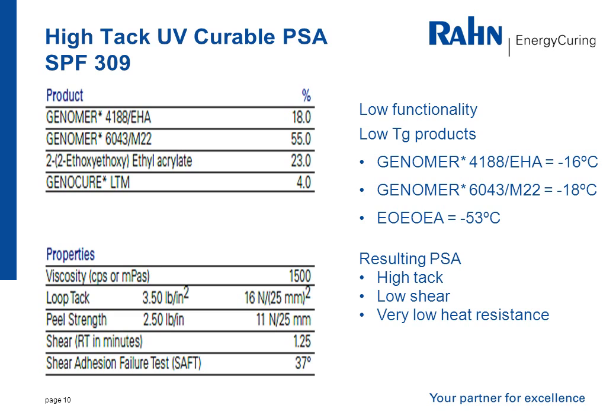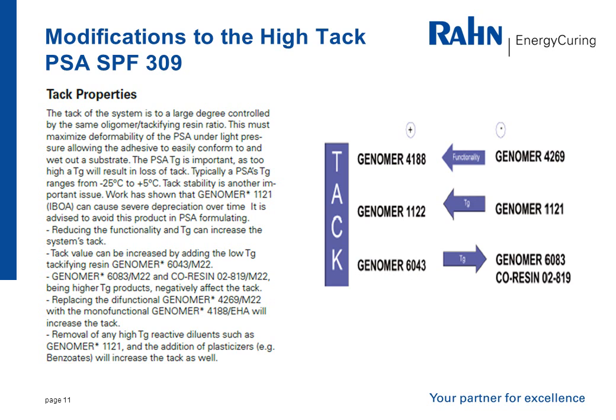The low functionality, low Tg products, 4188, 6043, and the diluent all work together, giving us a PSA that has high Tack, low shear, and very low heat resistance. Overall, a great formulation that gives us a high loop Tack of 3.5 pounds per inch squared. However, due to the low functionality products, cross-linking is limited, which results in low cohesion. The lab report also includes suggestions on how to modify your Tack properties. It is possible to adjust your Tack by changing your functionality and Tg.